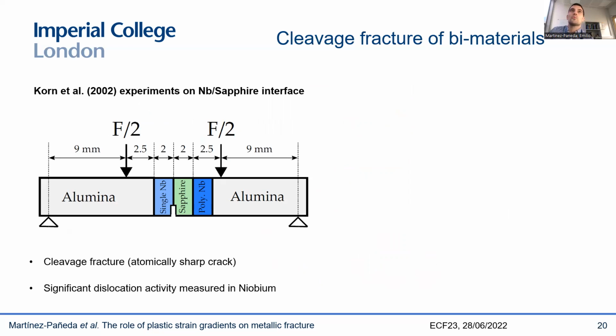So one of them is cleavage fracture in bi-materials. So the experiments by Korn et al. These are some classic seminal experiments where they had a crack between sapphire and niobium, and they measured very significant plastic work in niobium, but at the same time, when they looked at the fracture surface, they saw a very clean fracture surface with a crack propagating in a brittle fashion between the sapphire and the niobium,